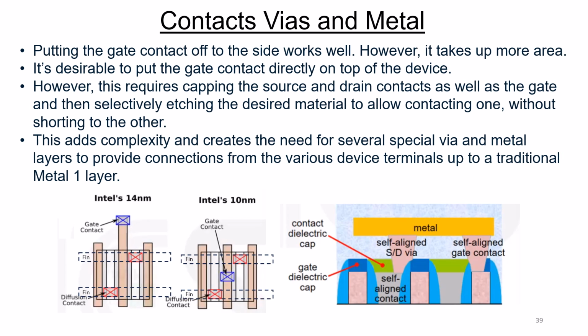Now, putting the gate contact off to the side, it works pretty well. However, it takes up more area, so it's desirable to put the gate contact directly on top of the device. However, this requires capping the source and drain contacts as well as the gate, and then selectively etching the desired material to allow contacting one without contacting the other. This adds complexity and creates the need for several special via and metal layers to provide connection from the various device terminals up to a traditional metal one layer.